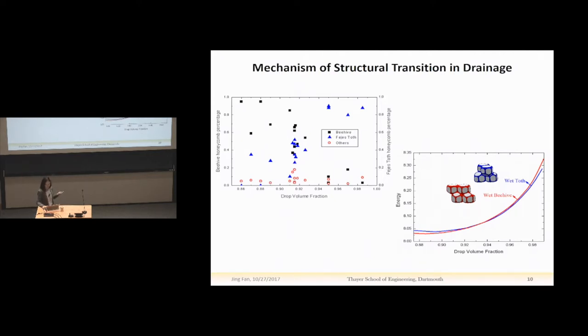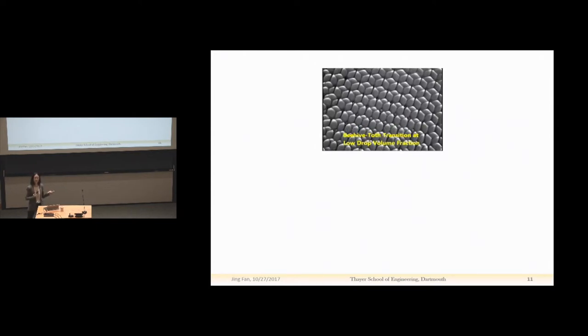But interestingly, in our experiments, if we look at the dynamic transition process within an emulsion system, we found that the transition can actually occur at a volume fraction much lower than the 0.935 predicted from the theory. For example, this video shows two examples with the structural transition. The first one happened at about 0.92, and in the second video, the transition volume fraction is only about 0.85. So there must be another reason besides the minimum surface energy.